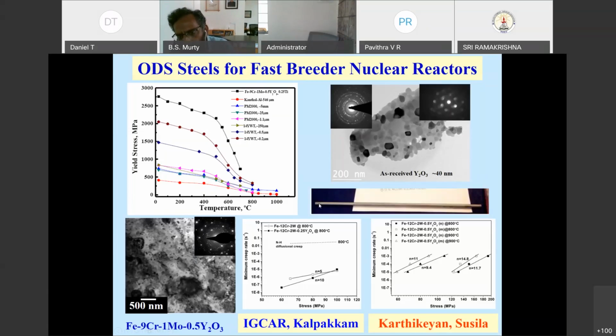We have been able to collaborate with IGCAR Kalpakam, NFC, and DMRL. We were able to produce a 4-meter long tube of a steel with these nanoparticles embedded in it. And such a tube, if you look at the mechanical properties, has a much higher yield strength than the traditional materials, even at 600, 700 degrees centigrade.